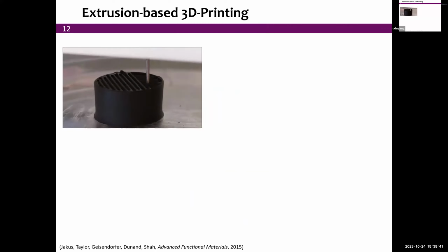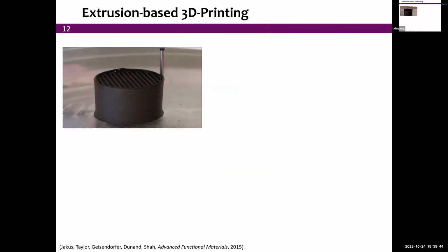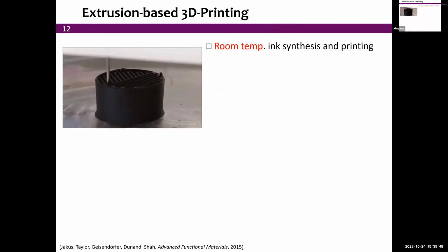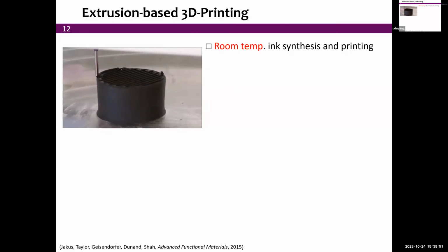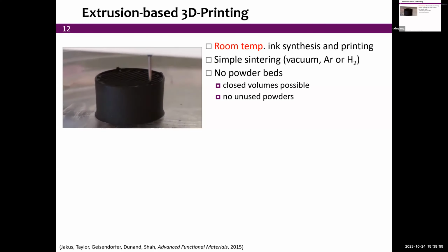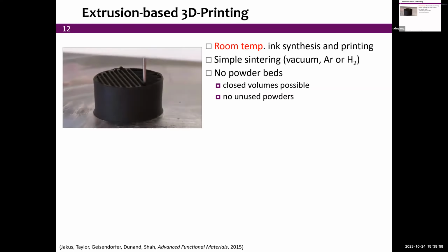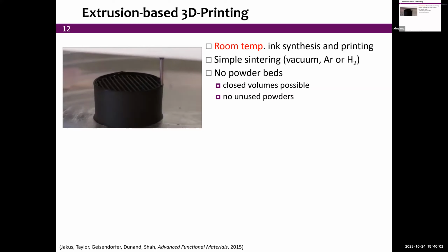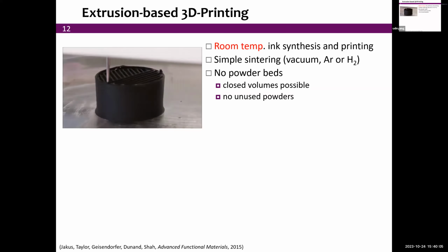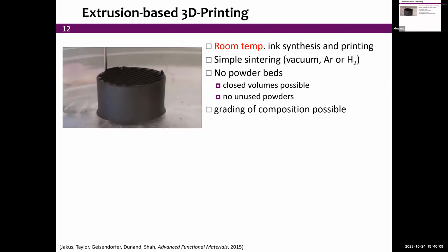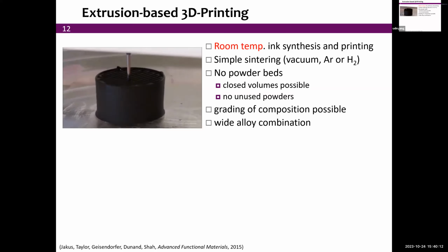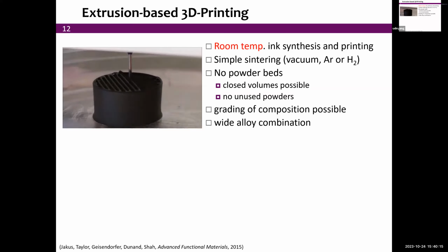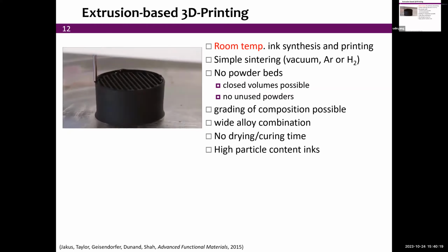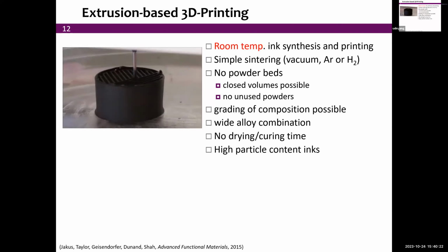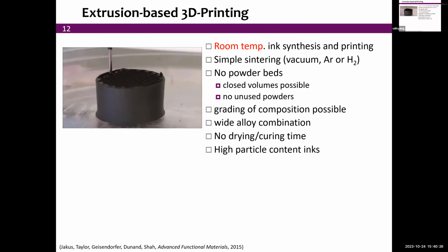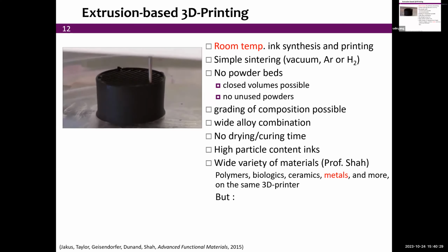So this is an example of ink printing of a highly loaded oxide powder material. And we can see the overall micro-lattice structure. This is room temperature for the synthesis and the printing. Very simple sintering. This is very standard vacuum, argon, or even hydrogen for the reduction. No powder beds, of course, which allows us to have closed volumes. We don't trap powders. We can grade composition with multiple nozzles, with alloy combinations if you are using blends of elemental powders or even pre-alloyed powders. Really no drying or curing time. This dries near instantaneously via fast evaporation, and really high loadings of particles, which is going to be important for the sintering step, because we want this to sinter.